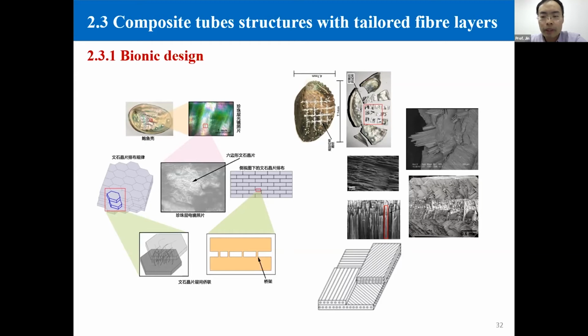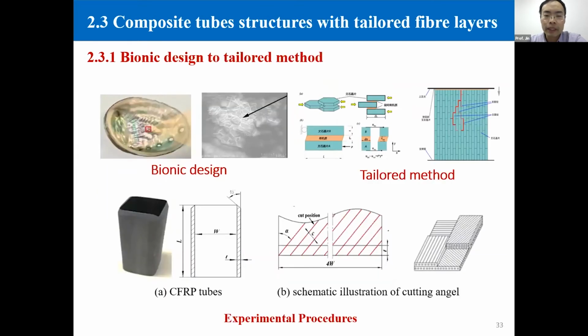If the fiber is not continuous, the impact energy absorption can be improved. Based on this design, we cut the continuous fiber into discontinuous fiber and get a better impact performance. So, our composite tube with a tailored composite layer.